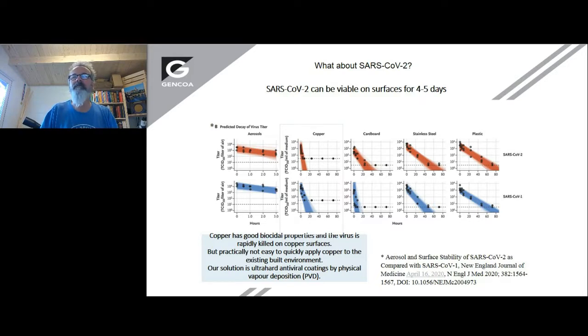If we look going to the right, plastics, stainless steel, cardboard. In fact, interestingly, cardboard was quite efficient at disrupting the virus, and that's probably to do with the cellulose, the nanocrystalline cellulose that's within wood. But plastics and stainless steel are actually very good hosts for COVID, so we need to do something about this. One thing we can do is utilize copper.